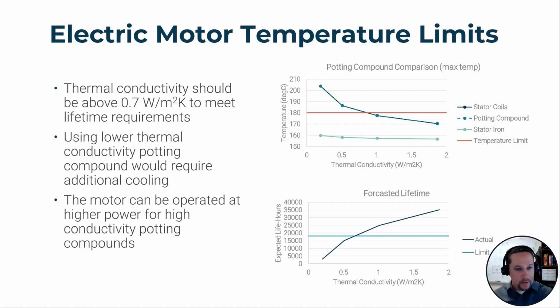And when we're looking at the temperature of the stator coils versus thermal conductivity, we can identify a point on that graph that corresponds to the temperature limit. And what we see is that the thermal conductivity should be about 0.7 watts per meter Kelvin to meet lifetime requirements. You can also look at the forecasted lifetime in expected life hours versus the thermal conductivity of the potting compound. And in that case, you can see what happens if you want to extend the life of your motor or operate it at higher powers and still get acceptable lifetime.